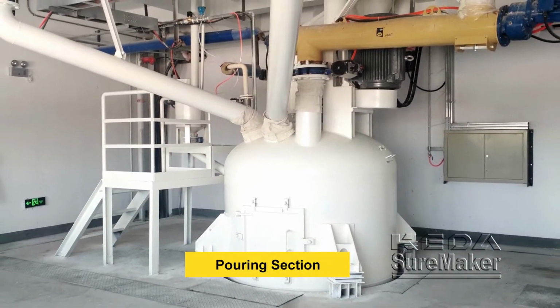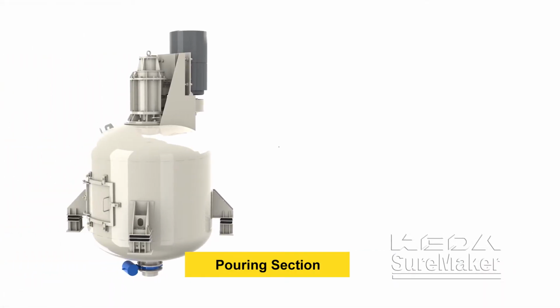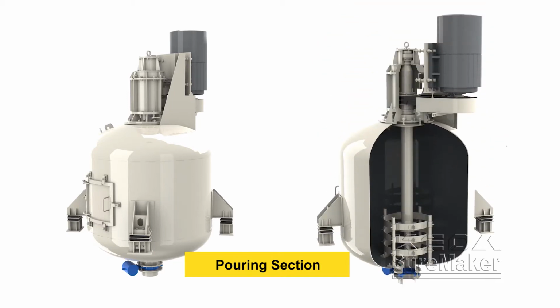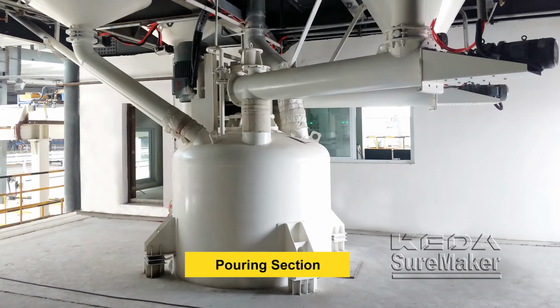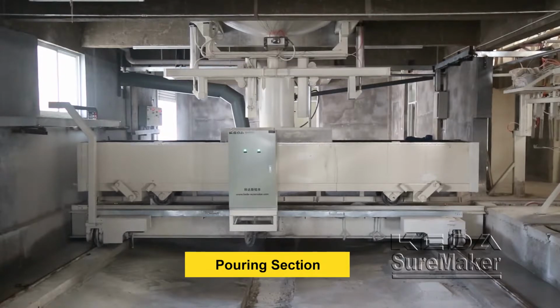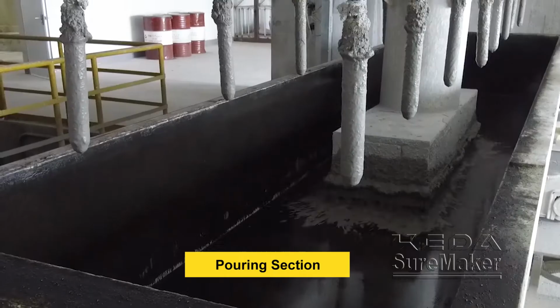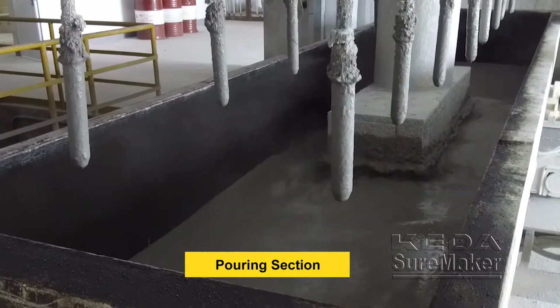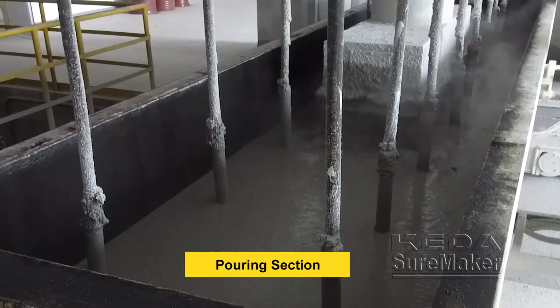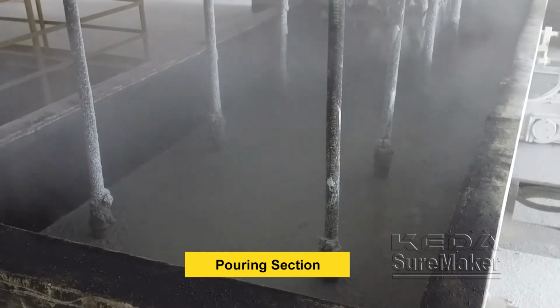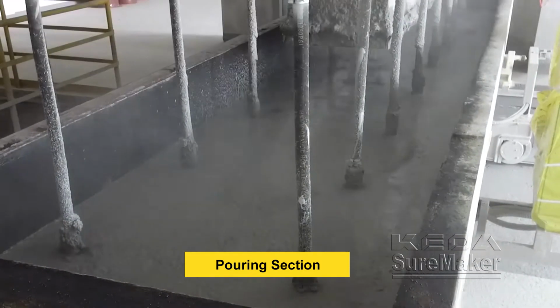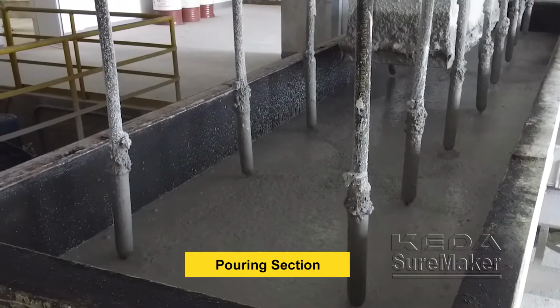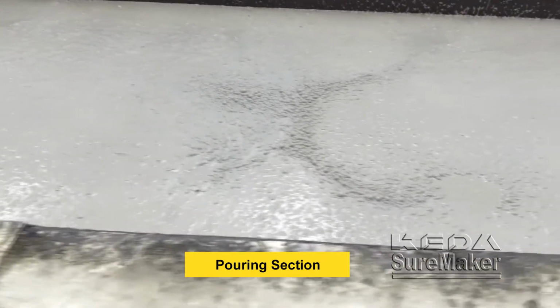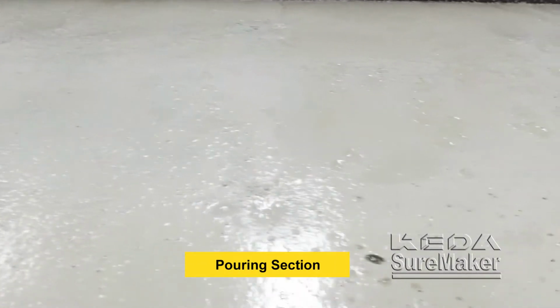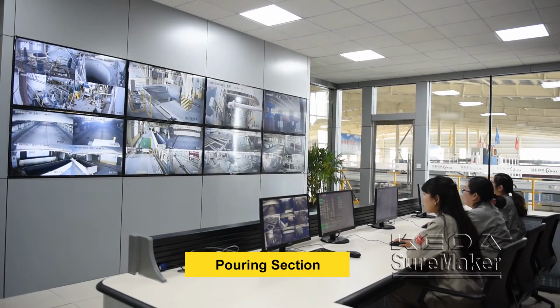With the structure of double cross paddle and modular draft tube, the pouring mixer can mix the slurry for producing AAC with density from 300 kg per cubic meter to 700 kg per cubic meter. The lifting pouring head efficiently eliminates big bubbles and prevents the oil layer from being washed away. Bubble treatment machine ensures uniform distribution of bubbles in slurry. The automatic batching control system ensures the accuracy and reliability of batching operation.